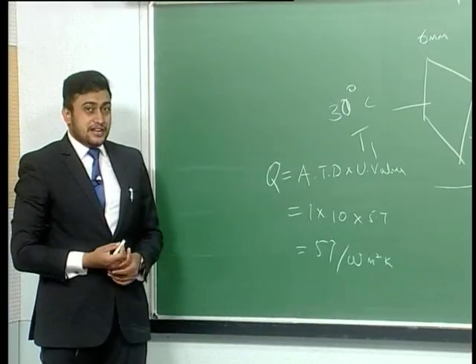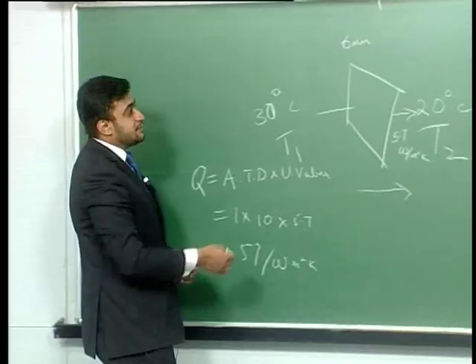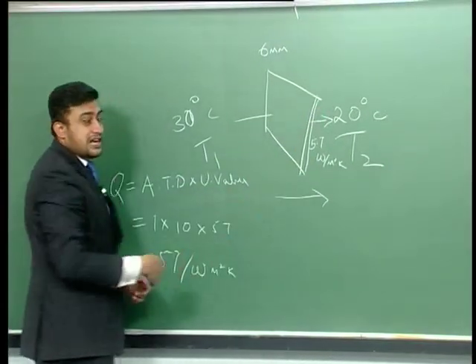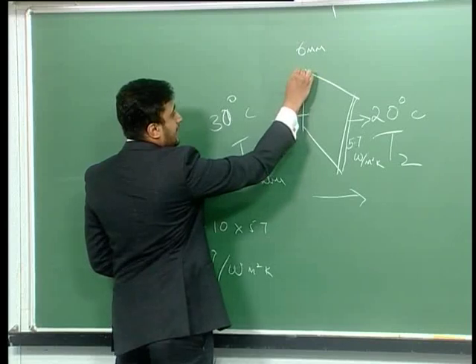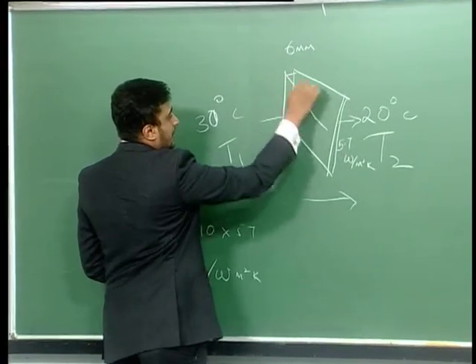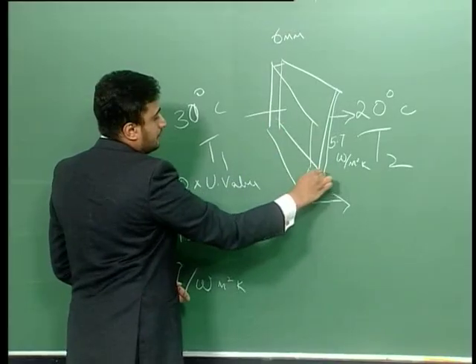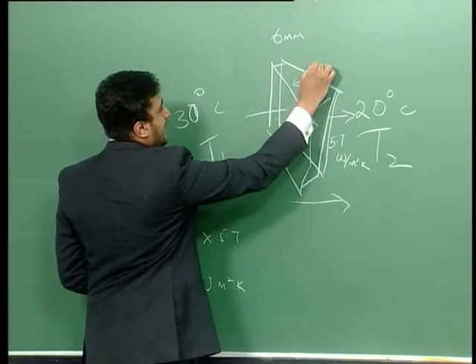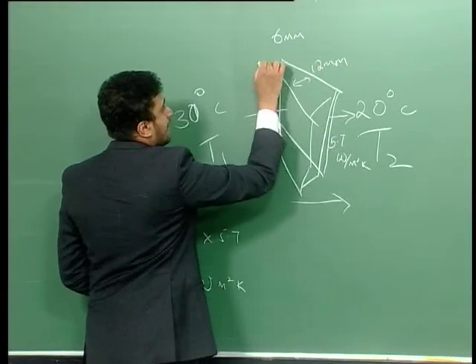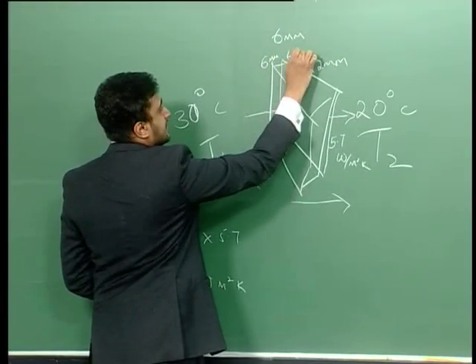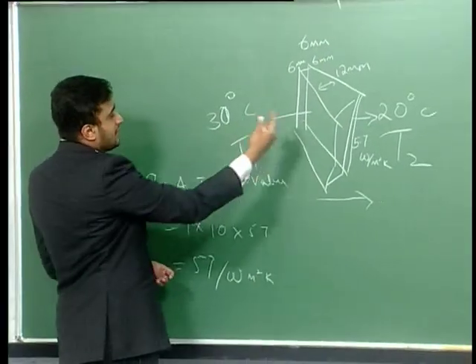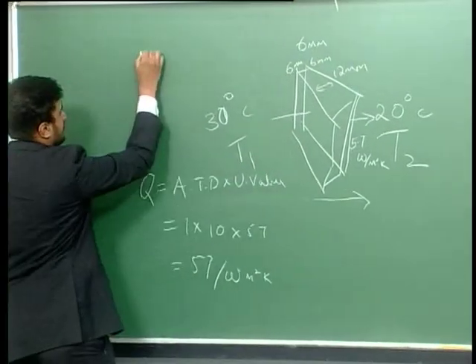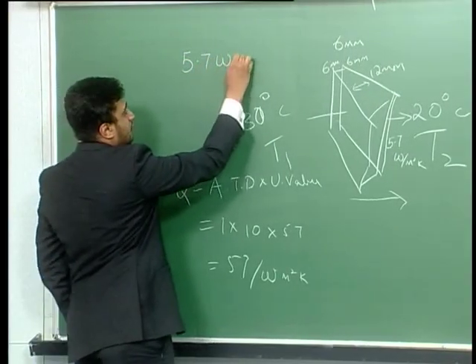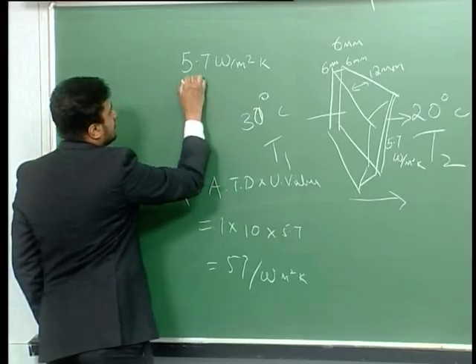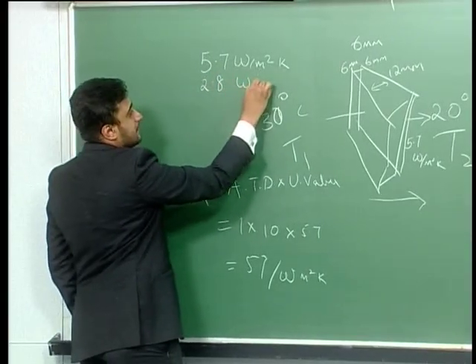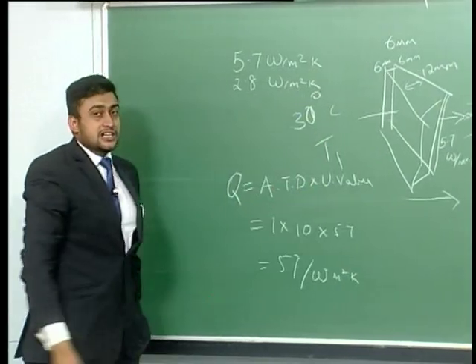Now this can be reduced by different measures. One is by doing a coating on the glass, we'll see how later. Another is by making the glass into a double glazed unit. So you have an air gap of 12 mm and you have 2 panes of glass inside. A 6 mm glass would reduce from 5.7 watts per square meter Kelvin to 2.8 watts per meter square Kelvin just by using a double glazing.